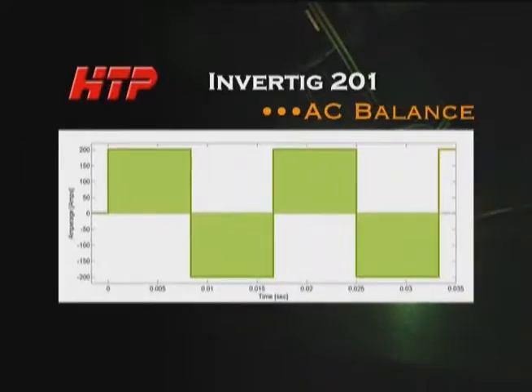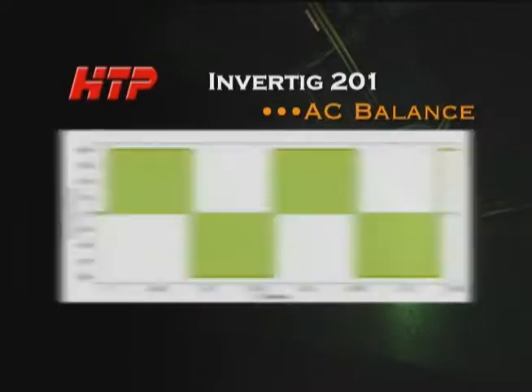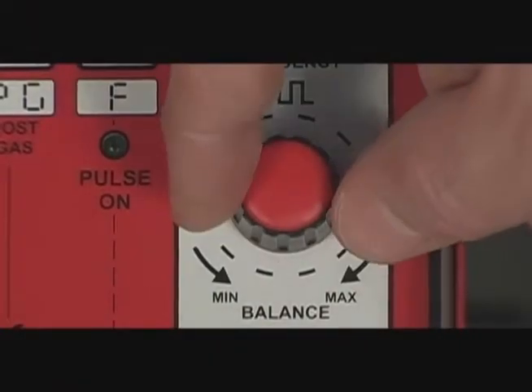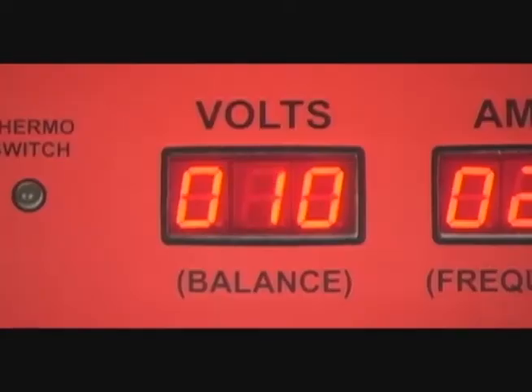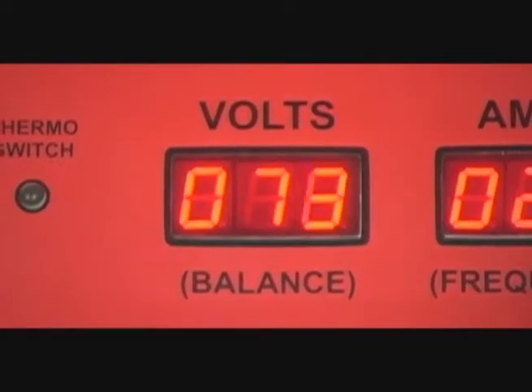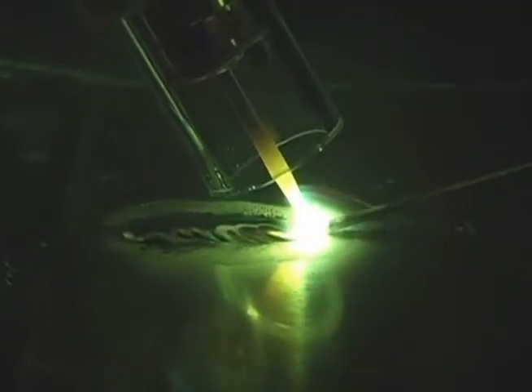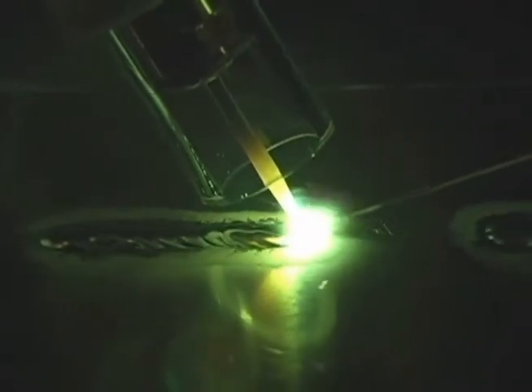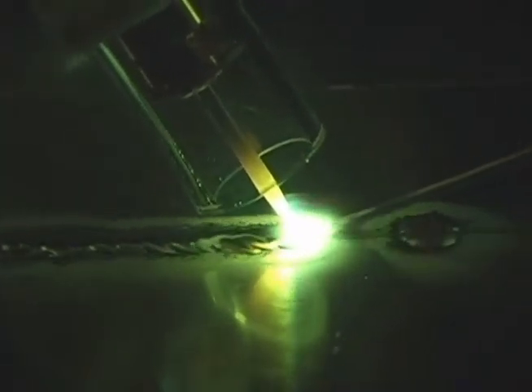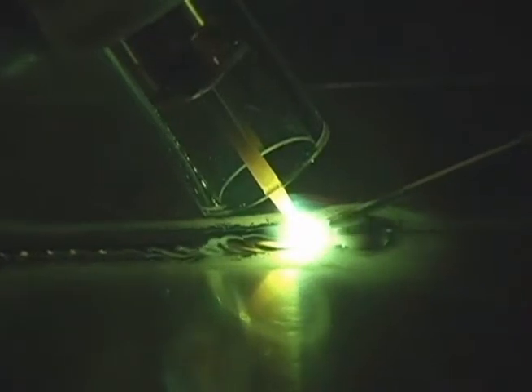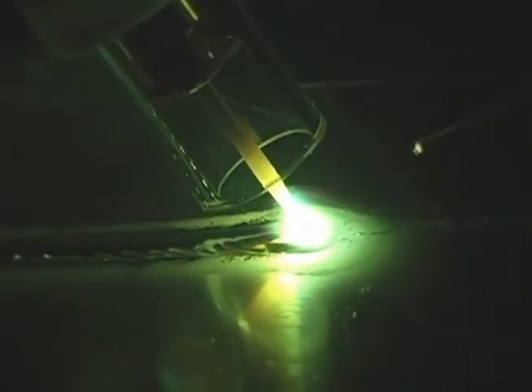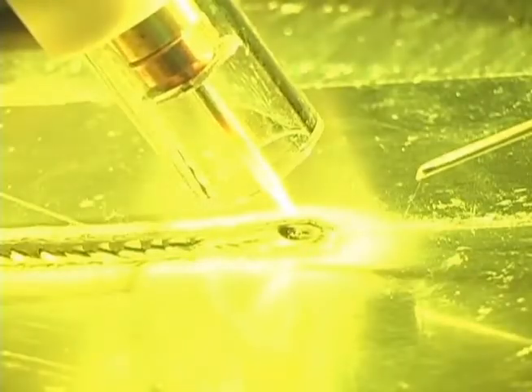A lower balance gives you more of a cleaning cycle, and a higher balance gives you more penetration. Finally, because of the ability to control the AC wave, it is possible to weld both steel and aluminum with one type of tungsten, and that tungsten will maintain a point even in the AC mode. With the arc jumping from a point instead of a ball, you get much surer arc starts and there is less arc wandering. The InverTIG 201 is truly the next generation in TIG welding equipment.